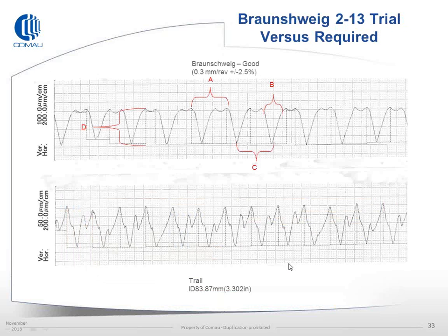When I was talking about how to quickly verify between different surfaces in terms of prep, this is an example of a Braunschweig, and what we're looking at is the wave profile of the prep surface versus a prep surface that ran 2% out of speed. And you can see that even with a good tool, a bad part could have been produced, but geometrically the numbers are completely wrong. Height-wise it is actually about half the height of a good prepared surface, as well as the wavelength is much shorter. So these are numbers that are easily calculated and measured and compared between different samples.